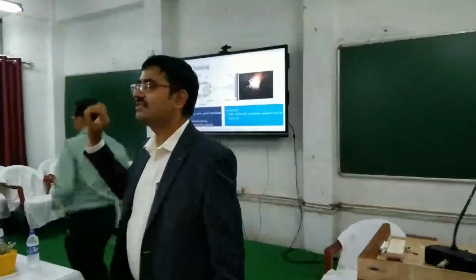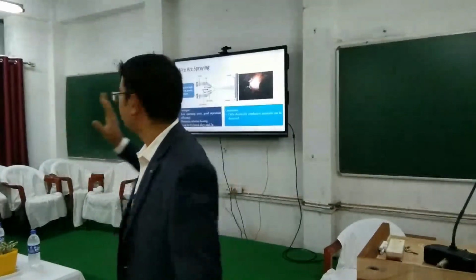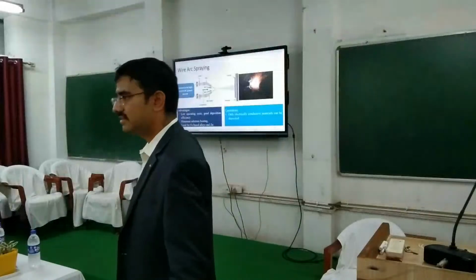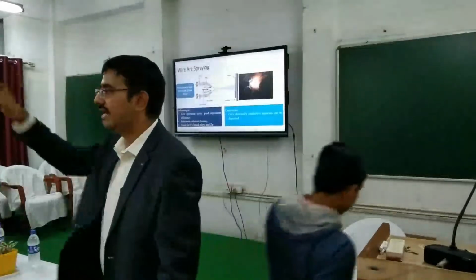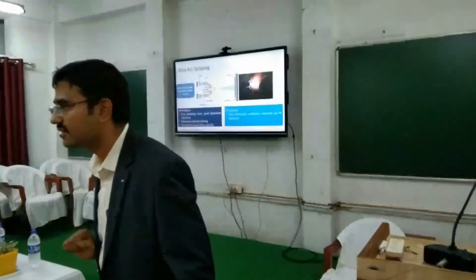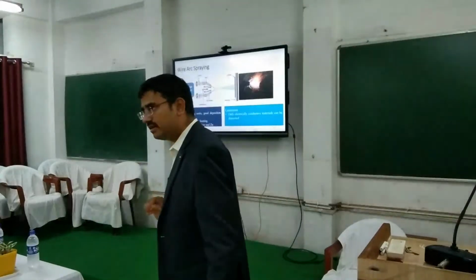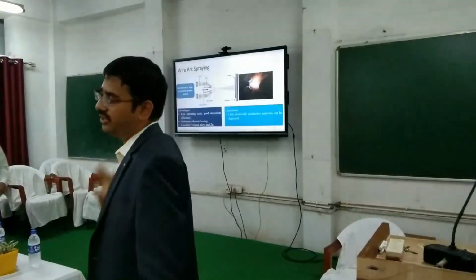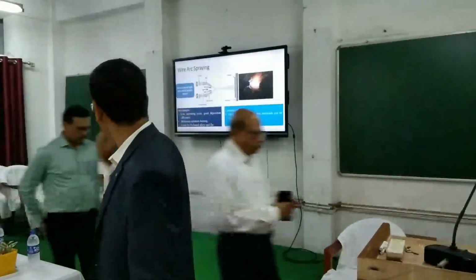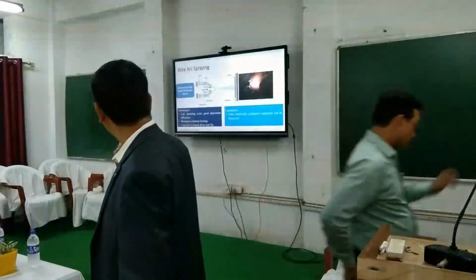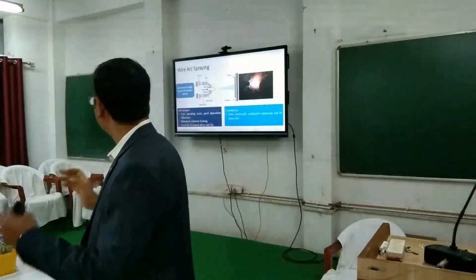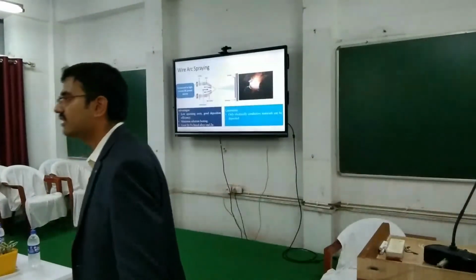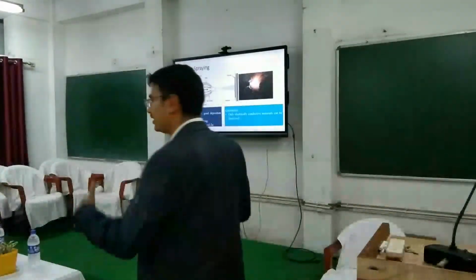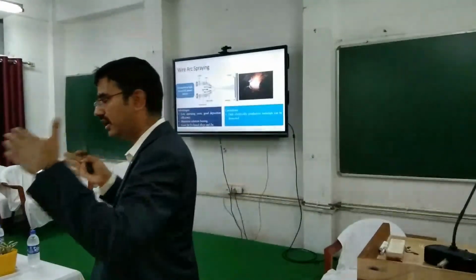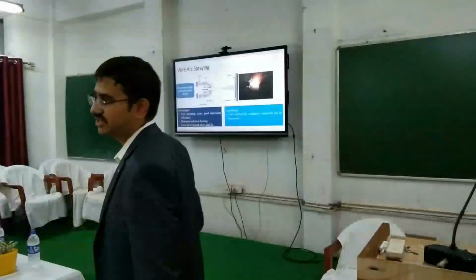If your substrate is temperature sensitive, in this case this is helpful because you don't have a hot gas stream that is hitting it. So some temperature sensitive materials can be coated using wire arc spray. But the limitation here is that your wires should be electrically conductive. That is one particular limitation. Otherwise, you will not have the conductivity and arc generation will be a problem.